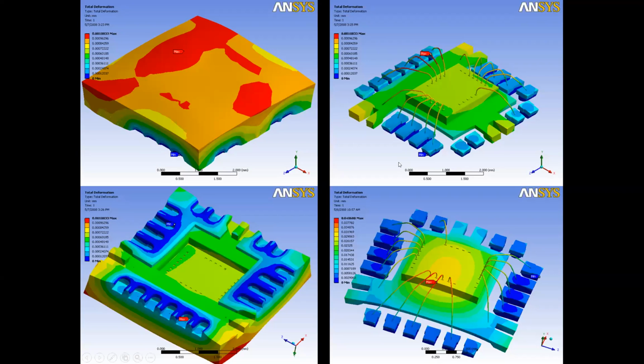The total deformation, interestingly, for such millimeter-based ICs of say 2 mm, 4 mm, or 9 mm, or maximum 10 mm dimensions, is about 1 or 2 or 3 or 5 microns of warping or bending, because of thermal stresses and strains that create some kind of warping. But this small deformation is enough to give von Mises or equivalent stresses of about 200 or 300 megapascals within the IC. So it's very serious.